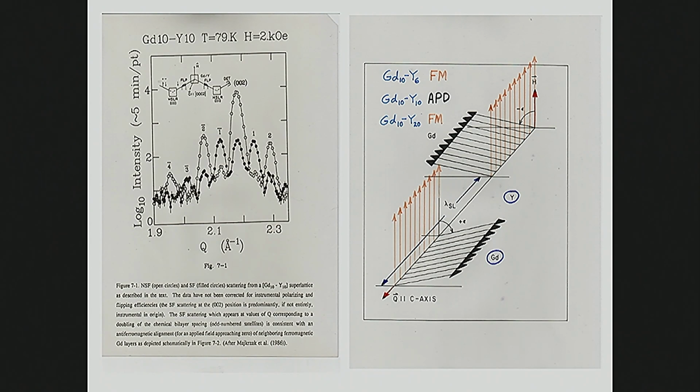It turns out, if you take a system like gadolinium yttrium, you have the gadolinium, again, all ferromagnetic, all pointing up in one direction. If I change the number of atomic planes of yttrium between this gadolinium slab of, let's say, 10 atomic planes and this one, you'll get all the spins to be up. But if I then make another system where the yttrium layer thickness is different, I find that they go almost anti-ferromagnetic in this canted state. No, not canted state, but spin flop state.